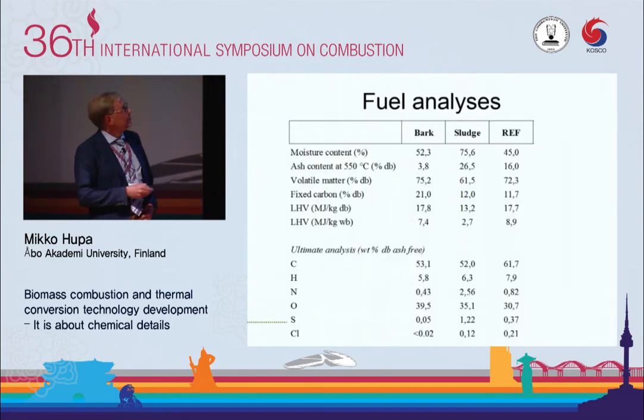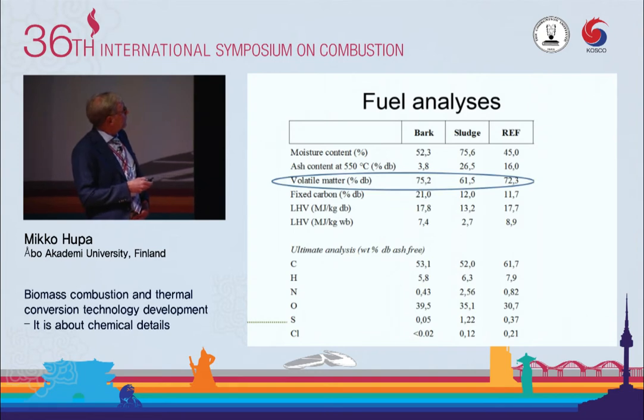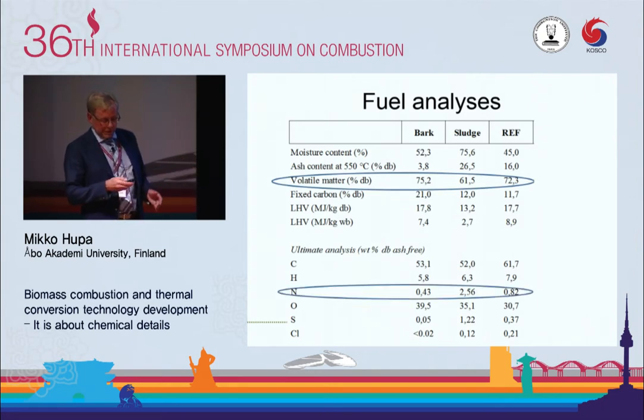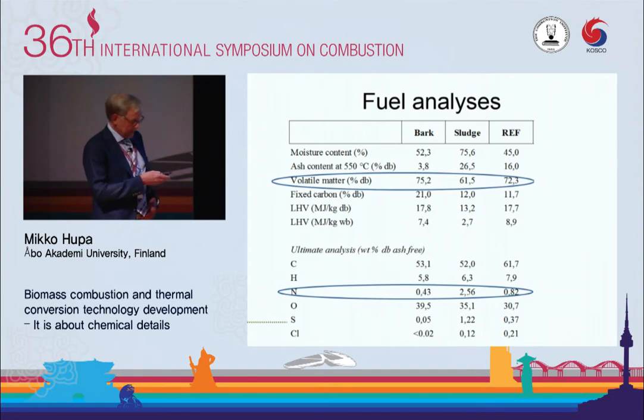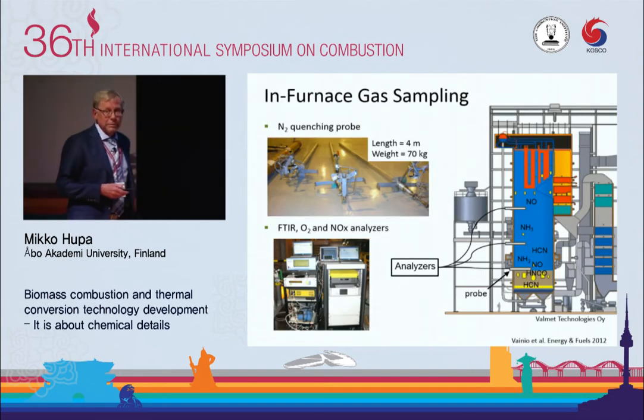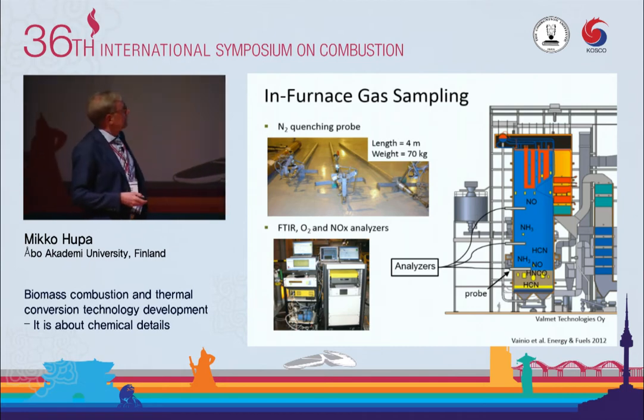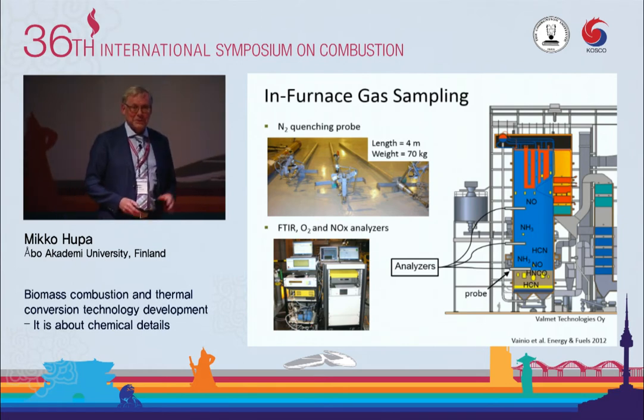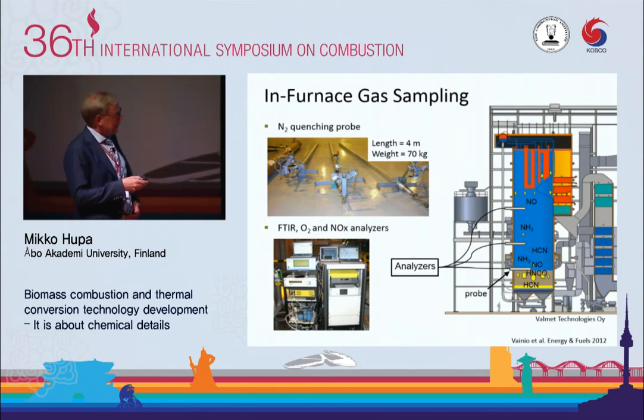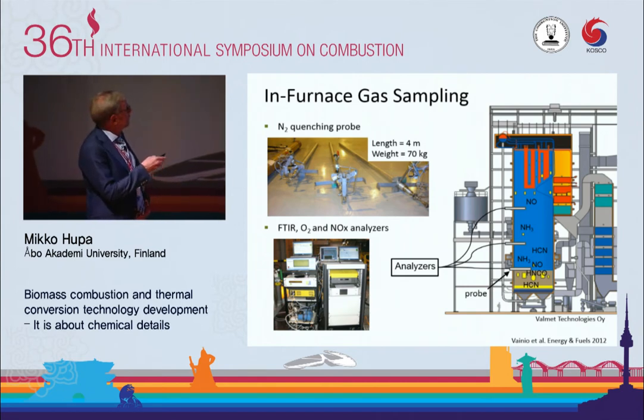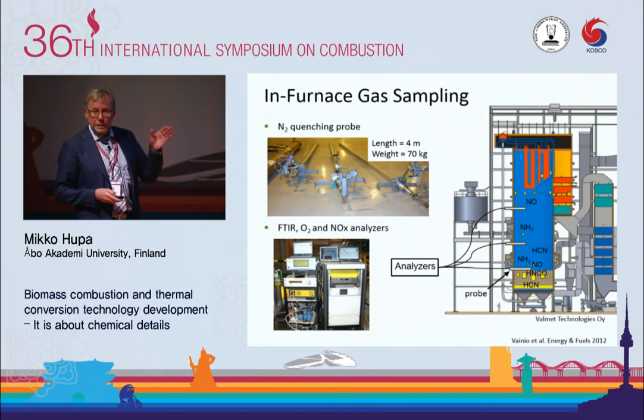This particular unit burns mostly bark, but it also has additional fuels. In our test, which I'm going to show, we were burning only bark. And you see the nitrogen content in bark is about 0.4. And I will show our equipment, because this was quite a challenging work. Now, I have great respect for measurements in the laboratory with sensitive equipment, but this is a different game when the equipment grows to 50 meters by 10 meters. We used large sampling probes, pipes, and we put them into different locations in a systematic way.